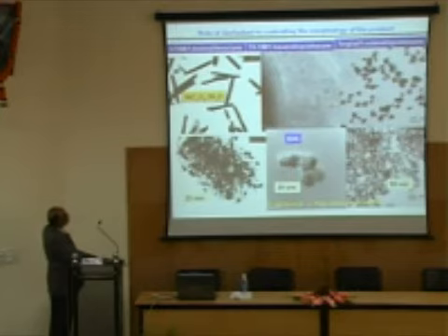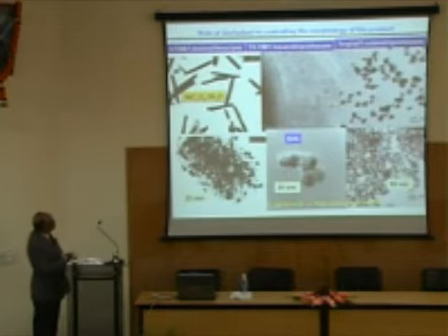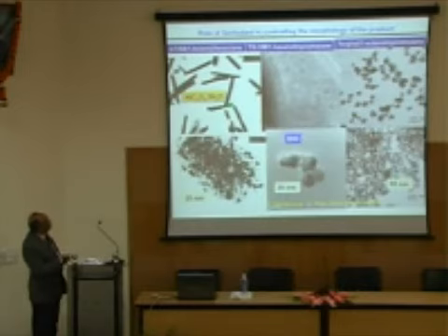This is again another case. You can go from a rod, same material, you can go from a rod to a particle to a cuboidal system. This has dimensions of around 40 nanometers in this direction and maybe around 70 nanometers in this direction. Okay? And these particles are around 6 to 7 nanometers. These are very small particles.